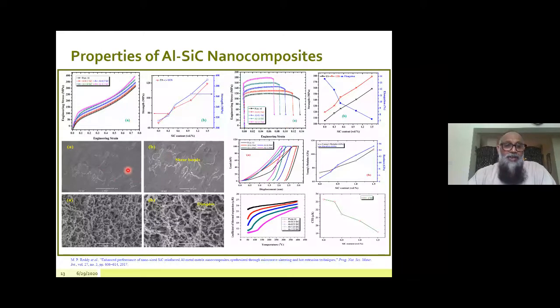So these are the fracture morphologies of the developed materials. The pure aluminum matrix shows a shear mechanism, shear bands, whereas in our developed composites, we have very clear dimples in the structure. We also studied the coefficient of thermal expansion of all the developed compositions. We can see that the coefficient of thermal expansion decreases with increasing amount of silicon carbide nanoparticles in the matrix.